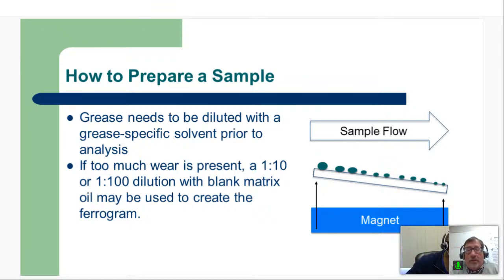Grease does need to be diluted with that grease-specific chemistry solvent prior to analysis. Fortunately, most of the greases that we process through our lab respond fairly well to a heptane toluene mixture that we use. When you start with that thin film, it's pretty effective for a lot of grease chemistries. But now, once you do that, you've got to look at what about the wear that's there. And in oil analysis, we sometimes have to dilute that sample when the wear is real severe. My experience with grease analysis is that we tend to have more wear particles than we do in your typical oil sample. So the dilution comes into play more often to achieve this separation.